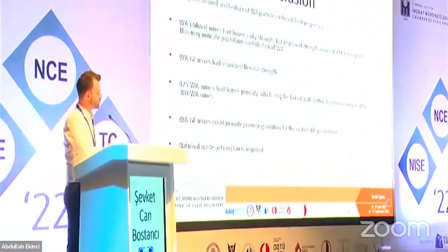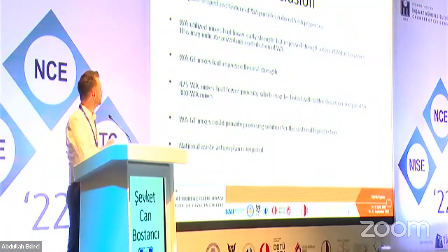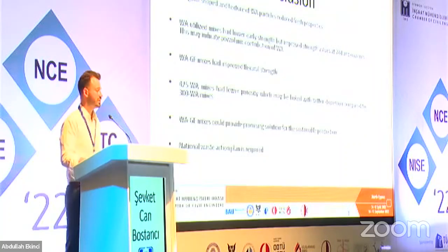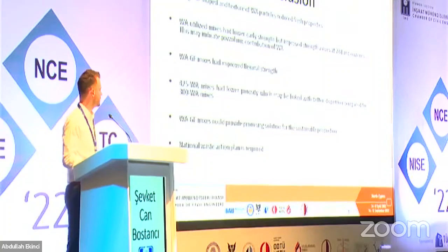Another aspect which I did observe in the concrete production is that 425 micron sieve wood ash mixes had lower porosity, and this may be due to better dispersion when it is coarser, and it's quite challenging when it gets finer. I am also investigating wood ash sieved to 150 micron in my research. It could give us a promising solution for sustainable production and promotion of sustainability.